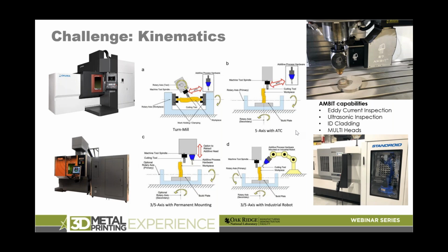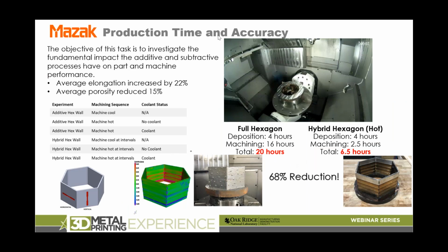With the wire welding, we get much faster deposition rates and we can build much faster. But with the powder, we get much higher resolution. So it's really unclear which route is going to be the winning route, and they all have their pros and cons. So this is a demonstration of the Mazak machine.